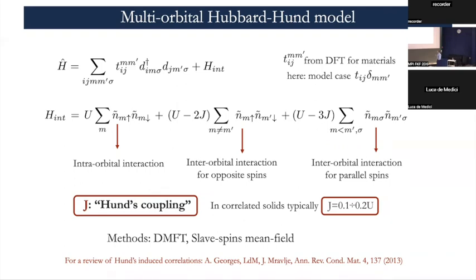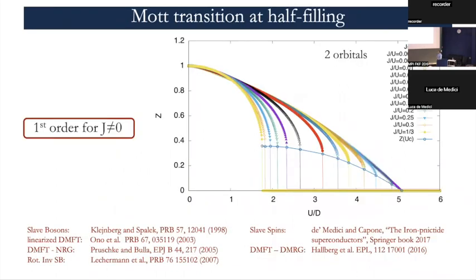We use dynamical mean field theory or slave-spin mean field, which is a simplified way to solve the equations in the spirit of dynamical mean field. The main result about this two-orbital Hubbard model with degenerate bands and Hund's coupling is that you have a Mott transition at half filling, which is depicted here by looking at the quasi-particle weight Z, which at zero interaction strength is 1 and then goes down, showing the degree of metallicity, and when it vanishes, you have a Mott transition. Now, the message of this figure is that as soon as you have Hund's coupling, this transition becomes first order.